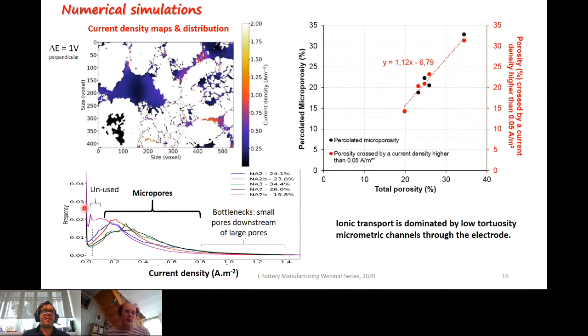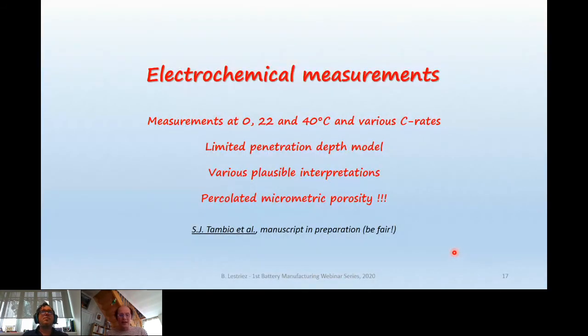And as a matter of fact, if you look at the distribution, you can see that there is a certain amount of porosity that is crossed by a zero or negligible current. So we have set an arbitrary threshold of 0.05 ampere per square meter. And when you compare the amount of the porosity that is crossed by a current density higher than 0.05 ampere per square meter, you realize that it matches the amount of percolated microporosity. So this is another evidence that ionic transport is likely dominated by the low tortuosity micrometric channels through the electrodes.